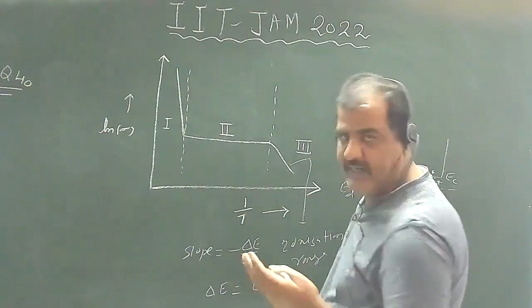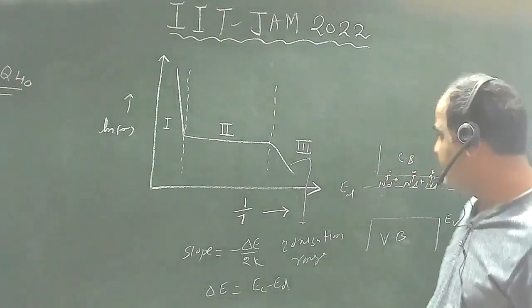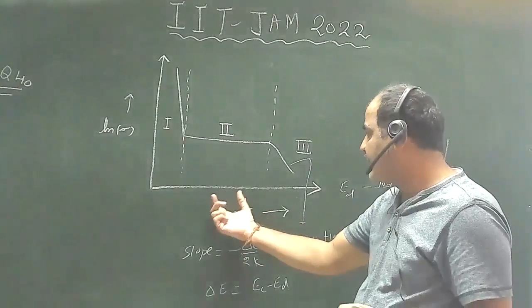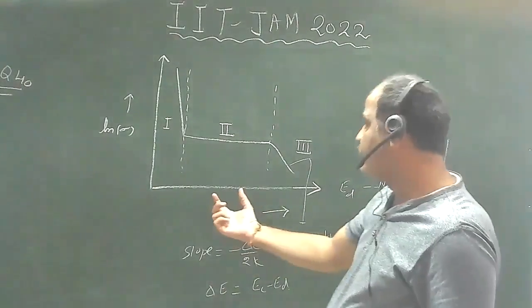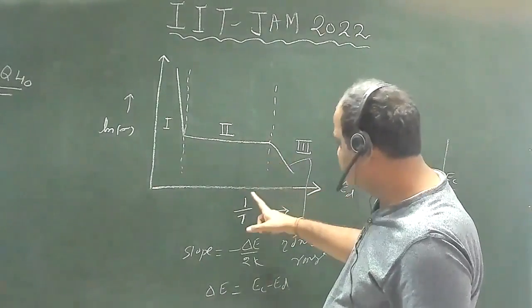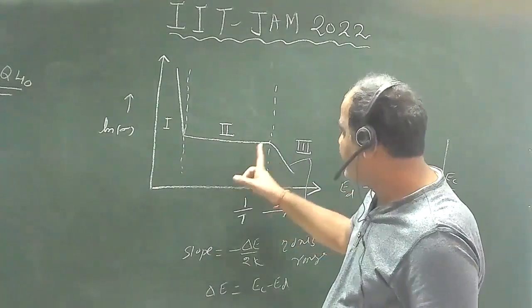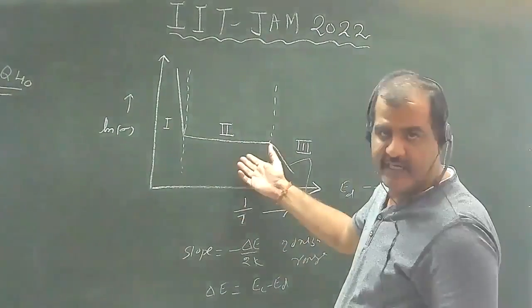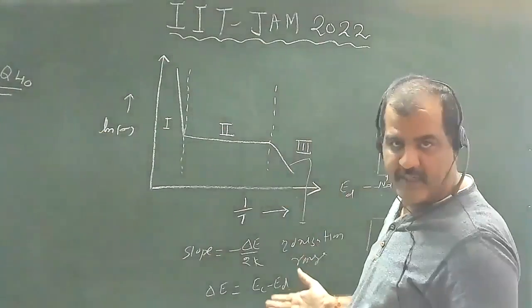That's why doped silicons are very important, because they give high or enhanced conductivity at room temperature. Once you go from region 3 to 2, you are increasing the temperature, but conductivity will not increase, because there are no more electrons available to enhance the conductivity, since all the atoms are already ionized.